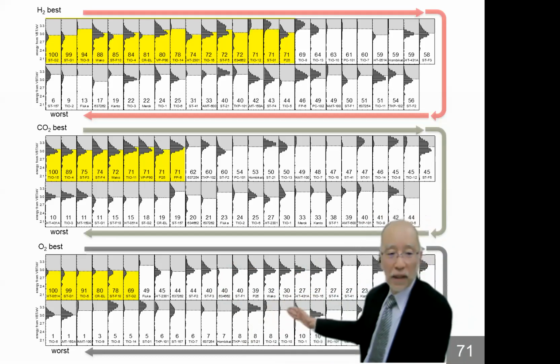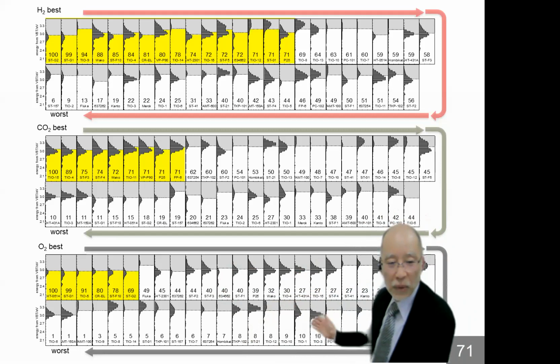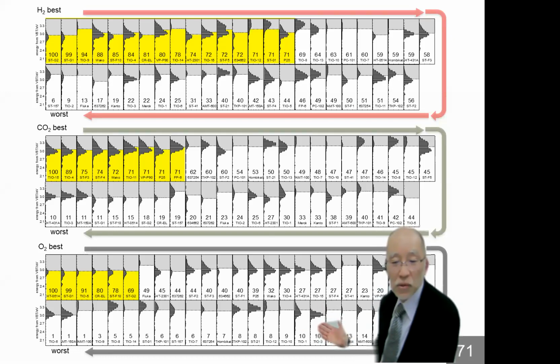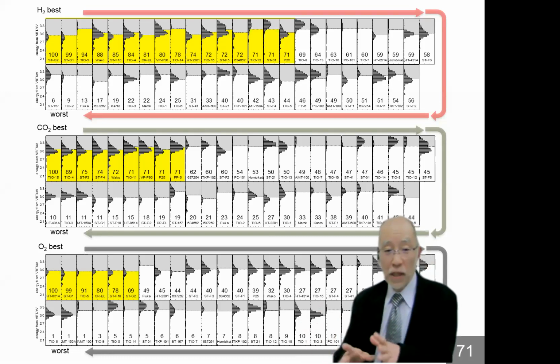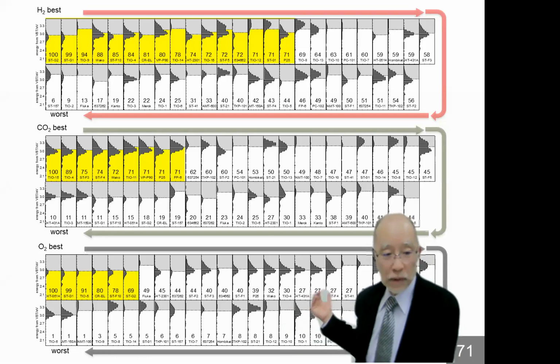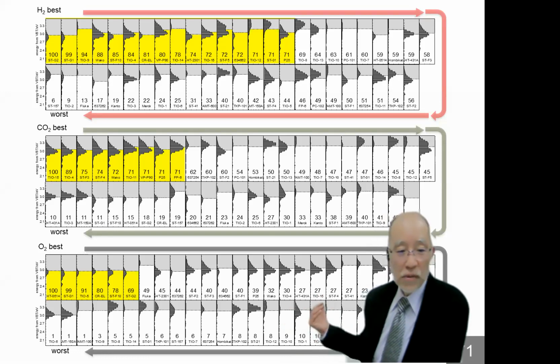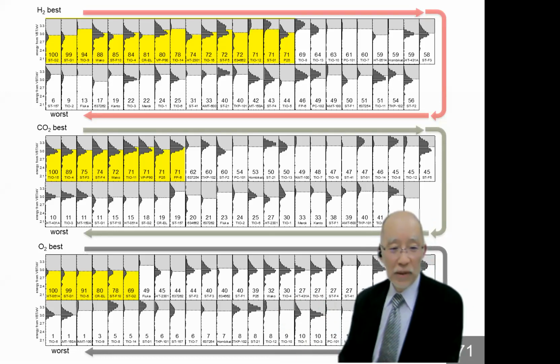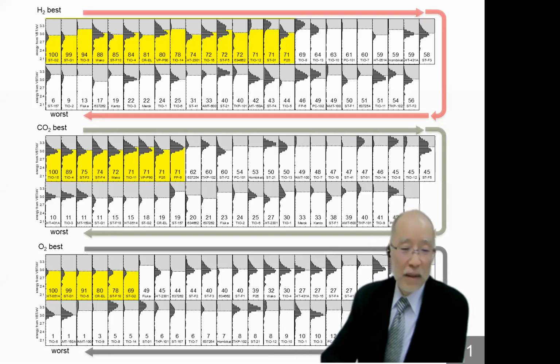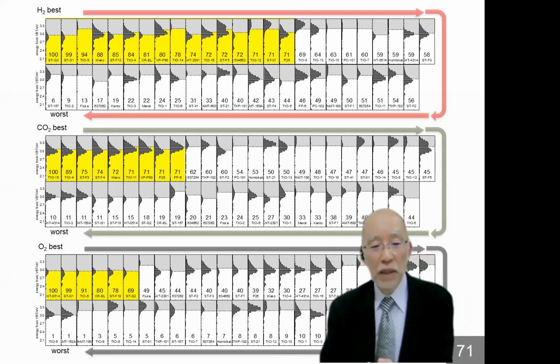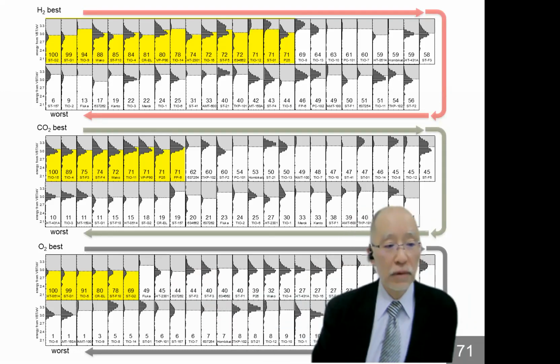So for example, this low activity sample, even if we could clarify why this sample is not so high, for example, that its specific surface area is very small or there are some defective sites here. But if that is improved, there is no guarantee of high activity, because the other parameter may give lower photocatalytic activity. So therefore, it is necessary to be well balanced like these higher activity samples.